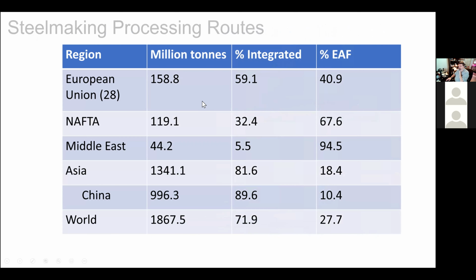So steelmaking processing, as I said, the two main processing routes are integrated steelmaking and electric arc furnace steelmaking, EAF steelmaking. So if we look at the European Union, about 60% of their production is based on integrated steelmaking. And they're going through a massive overhaul because in order to reduce the carbon footprint of their steelmaking, they're going to have to transition to a much higher percentage of electric arc furnace steelmaking.